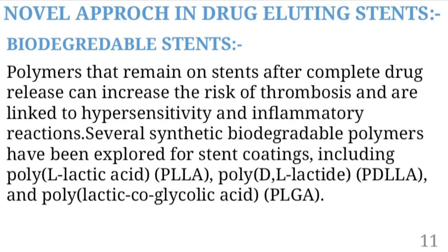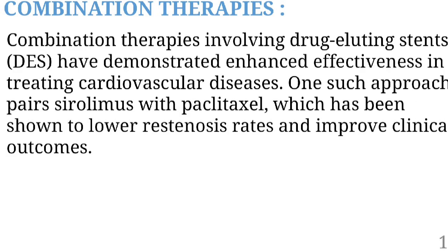Novel approaches in drug eluting stents. Biodegradable stents: polymer that remains on stents after complete drug release can increase the risk of thrombosis and is linked to hypersensitivity and inflammation reactions. Several synthetic biodegradable polymers have been explored for the stent coating, including polylactic acid, poly(D,L-lactide), and polylactic-co-glycolic acid (PLGA).